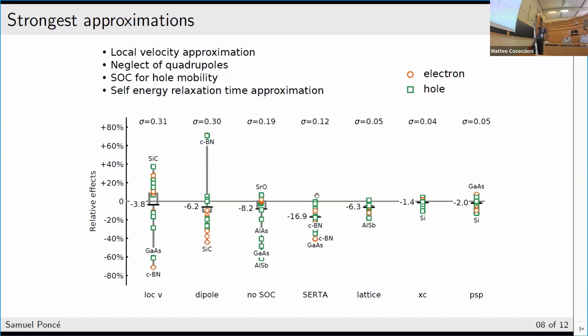You can see that you have some changes, maybe 10% at most. Squares are hole mobility, circles are electron mobility. If you change the exchange correlation functional, in this case if I remember it was PBE and then LDA, the change is even smaller, because this is from the same pseudopotential library. It seems to slightly underestimate the band. Then lattice is the difference between the relaxed lattice and the experimental lattice. Again, you have a not too large spread. Now, SERTA is quite interesting. This is when you neglect this second order term. This can be connected to neglecting backscattering and so on, if you connect that to phonon transport. In that case, you almost systematically underestimate. If you do the self-energy relaxation time approximation, this is very consistent: you will always underestimate. If you do the full iterative solution, you increase the mobility.